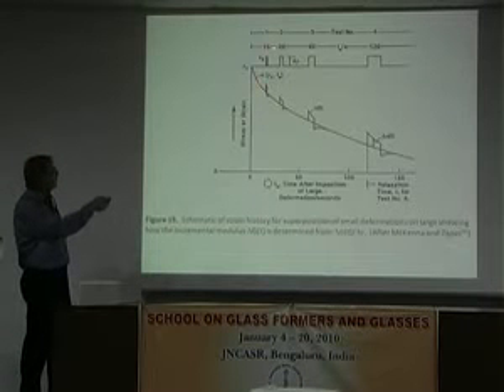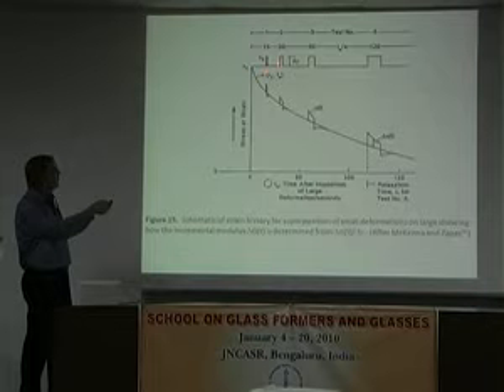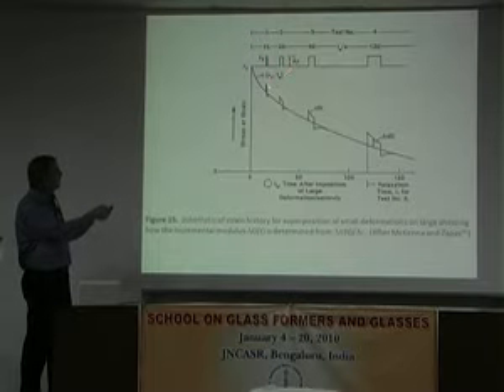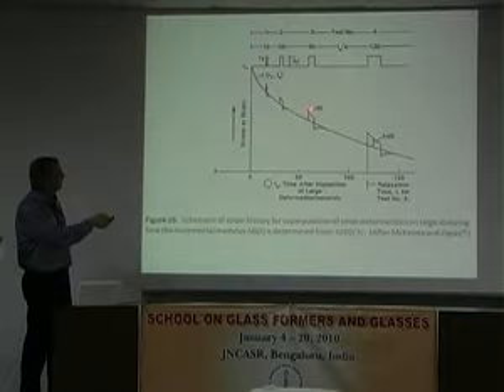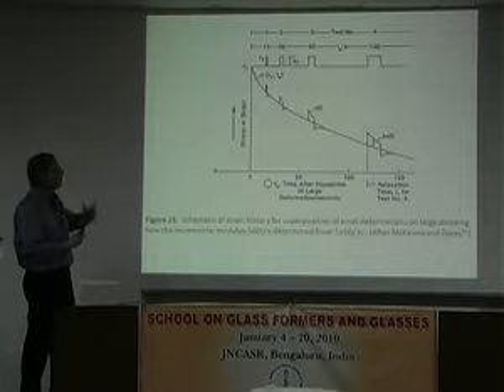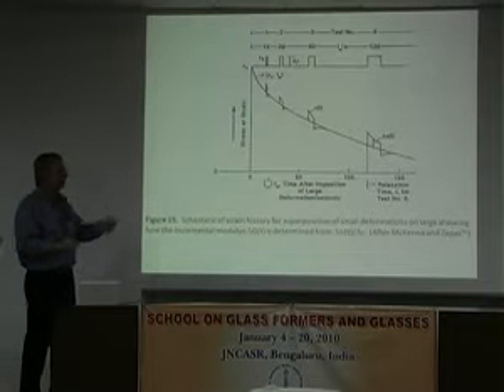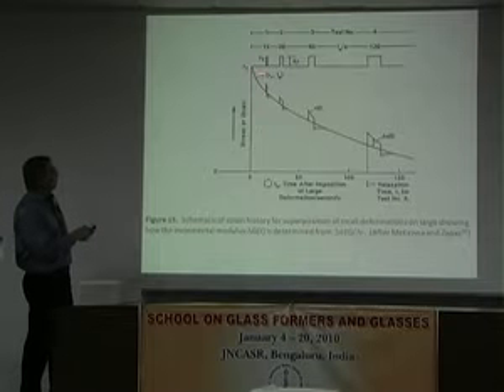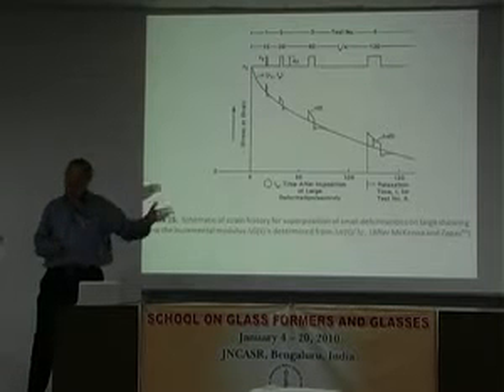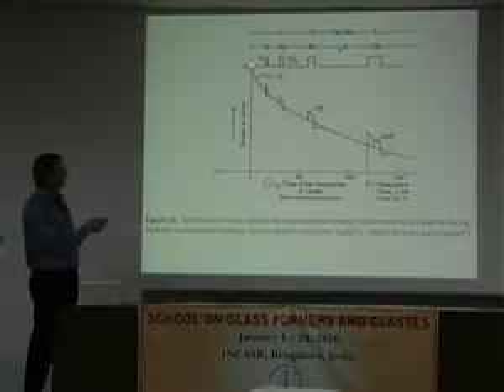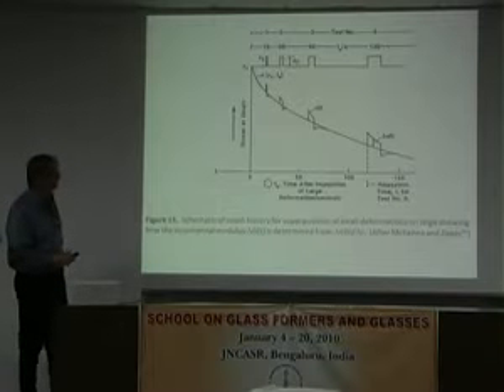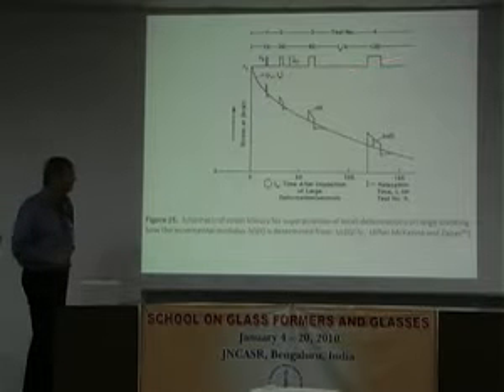And then you put a small strain on it and a small strain, and you're watching these stresses relax so you can get an incremental modulus. Okay? And so this protocol looks just like the Struik protocol after a temperature quench, but this is after, if you like, a mechanical quench. Okay? And then we're going to ask what happens.